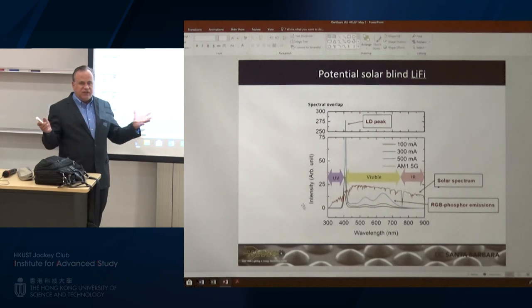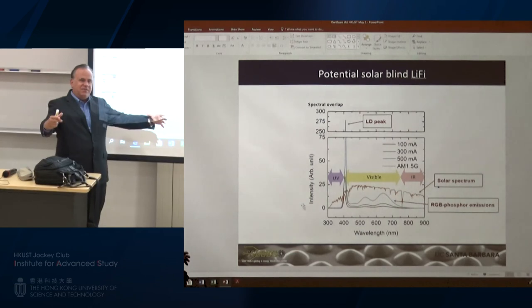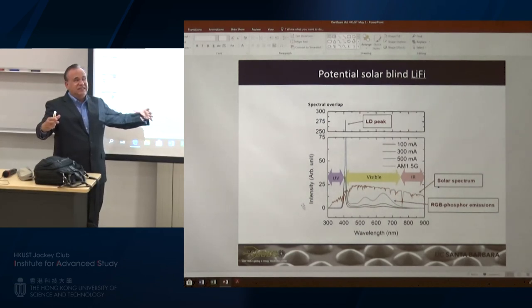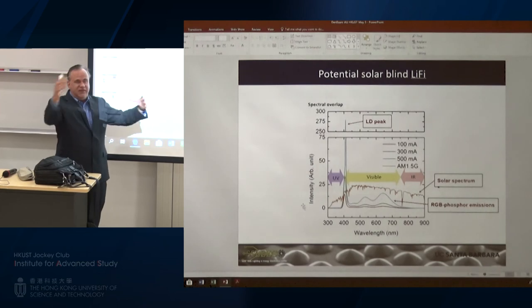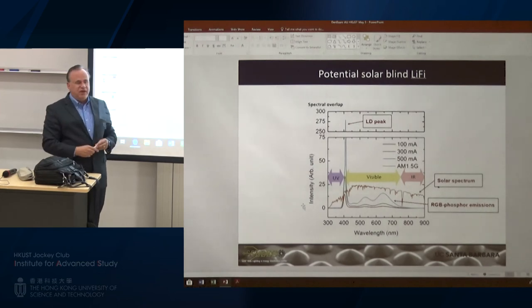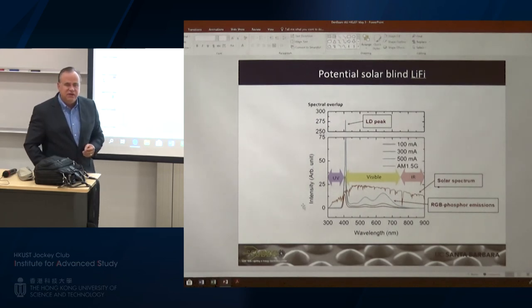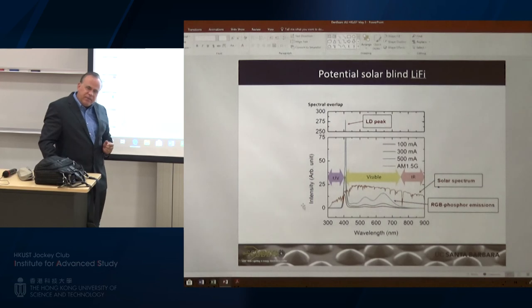Because a phosphor particle is 15 microns. If I'm making a 10 micron LED and you put a 15 micron phosphor particle on it, the conversion efficiency is not going to be good enough. You have to put a lot of 15 micron phosphor particles on. So people can't yet use a blue LED with phosphors for a microdisplay. Right. We come back to a single crystal phosphor. Oh, that's an interesting idea. So a single crystal phosphor would work. We wouldn't have the side dispersion problem. But the problem is the stopping coefficients. But what efficiency?